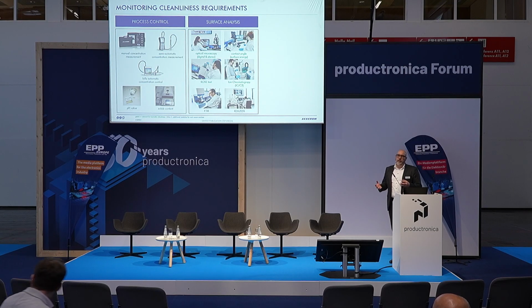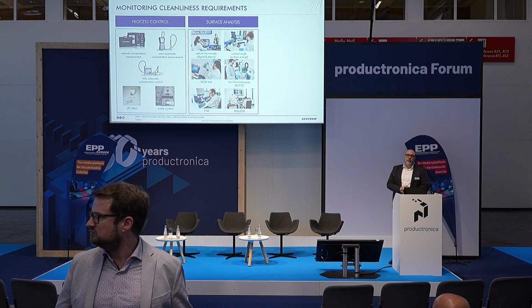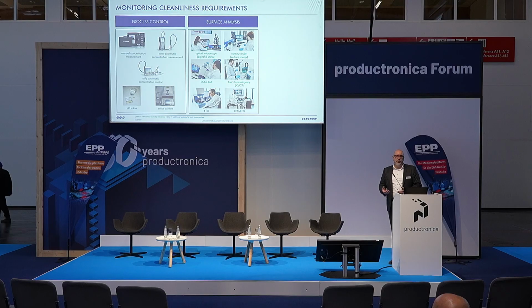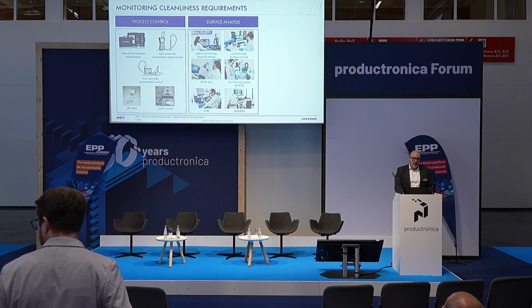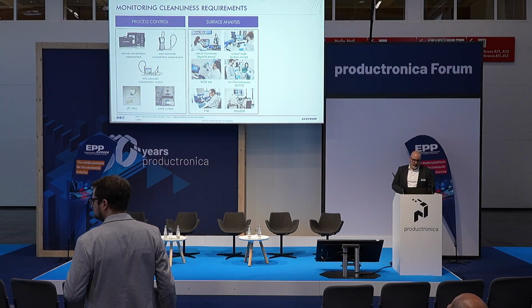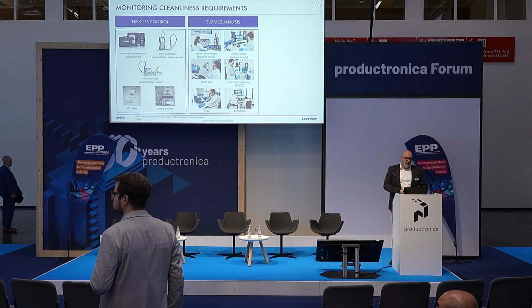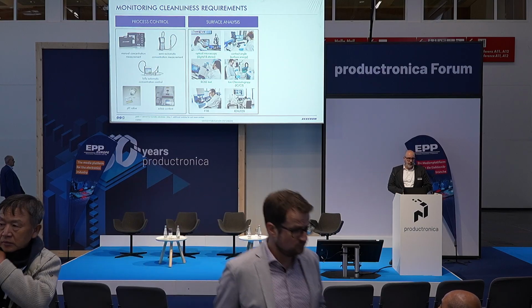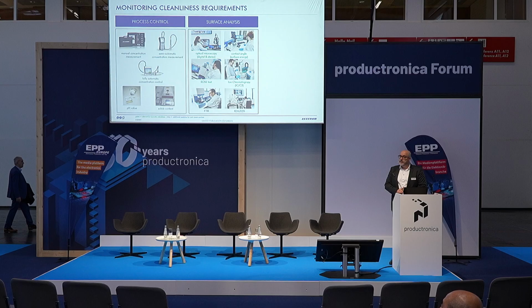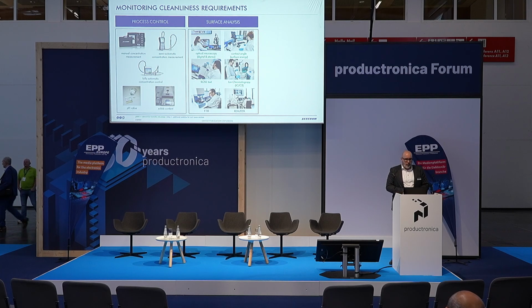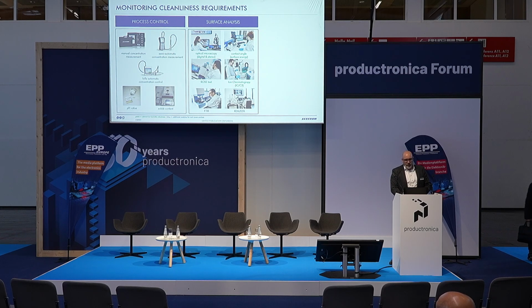Then, during the validation phase, but also after the validation in the mass production side, you need to check the surfaces for contamination and cleanliness. For this, there are different methods, like normal microscopy, contact angles for surface energy, ROSE and IC tests for ionic contamination, and for further analysis to really find the contamination materials and root cause analysis if you have some issues, the FTIR for organics analysis and the general EDX are very helpful.